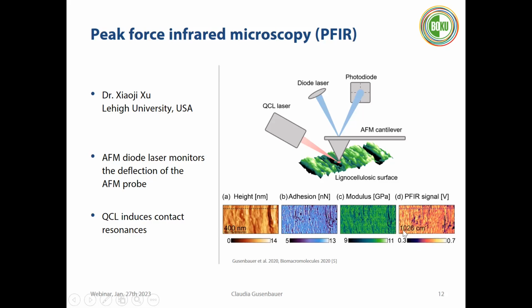So here we have the laser tuned to 1026, and we see where chemical components are situated, which have thermal expansion at this wave number. And we can also map adhesion and modulus because the tip is in peak force tapping mode, as the name already tells us. In this mode, we can also deliver adhesion information and information about the elasticity. So we also get modulus information when the tip is in the oscillating movement and is touching the sample, giving us typical modulus information by indenting the tip into our sample.